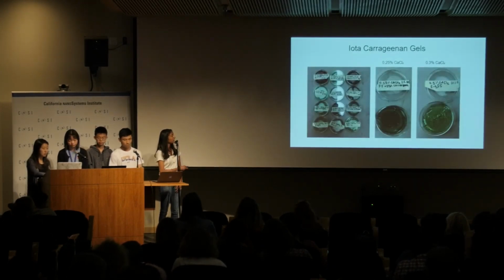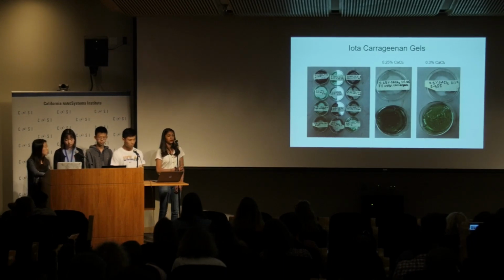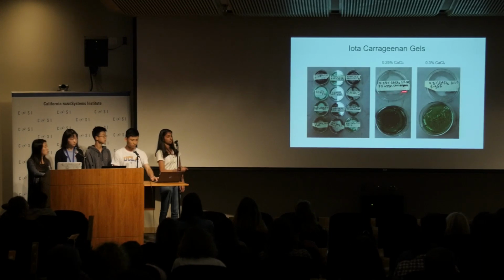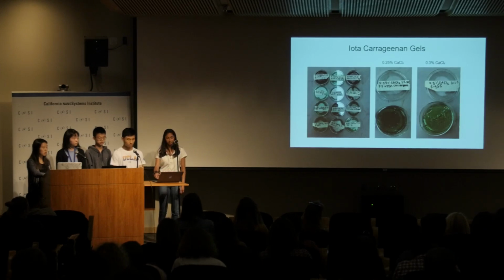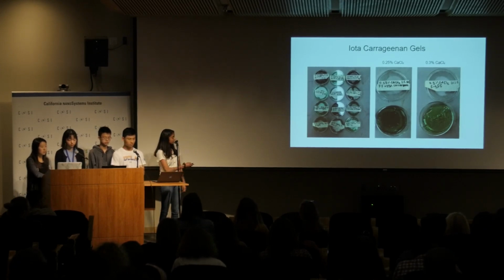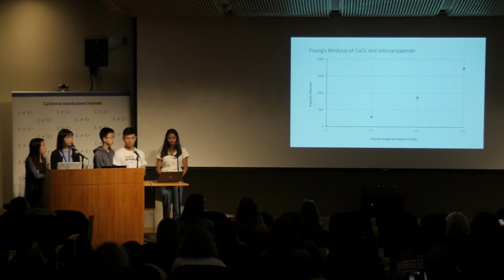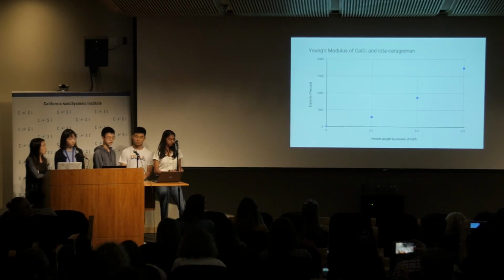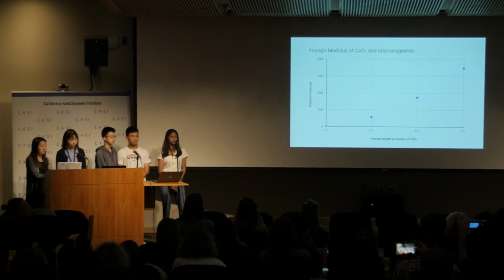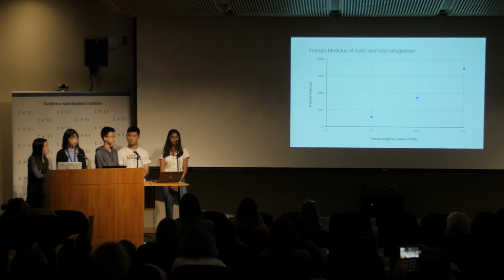As you can see here, these are all of our gels for iota-carrageenan and CaCl2. This is the 0.25% CaCl2, and this is the 0.3% CaCl2, which we found most ideal. As we tested our Young's modulus, we found that the more CaCl2 we put in the gel, the higher the Young's modulus was.